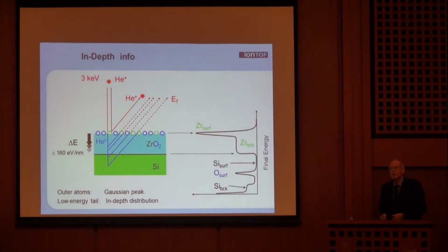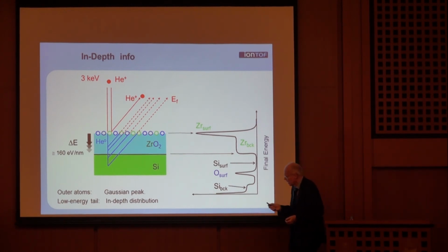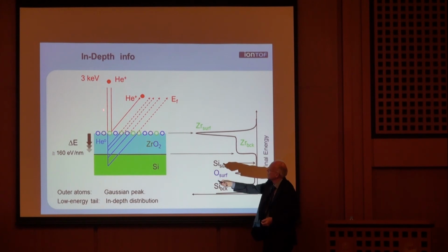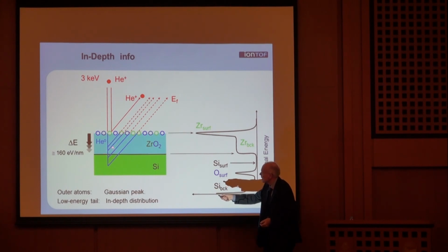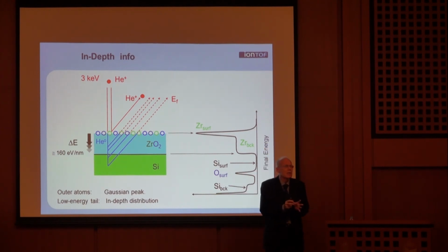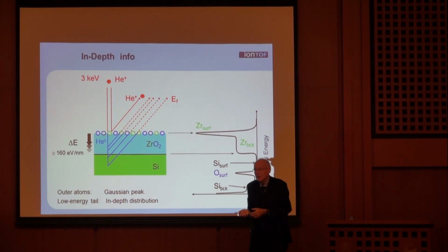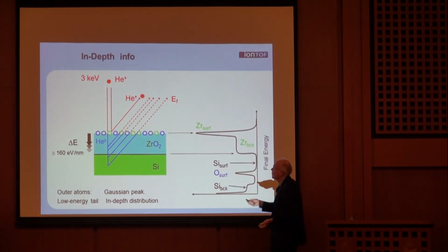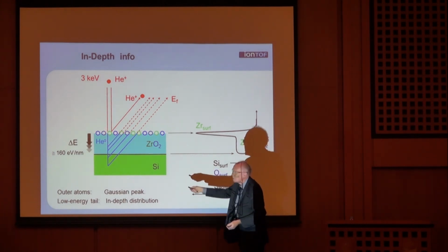Now, the last information we need before we get to real applications is that the ions come in, they scatter from the surface. Many of them go deeper and may scatter back there. However, helium is a noble gas atom, which means that once it gets to the surface, it likes to get electrons. It likes to be neutral. There's no element in the periodic system that can compete with helium. It has the highest electron affinity of all elements. And so, after penetrating, it becomes neutral. Okay, may scatter back.